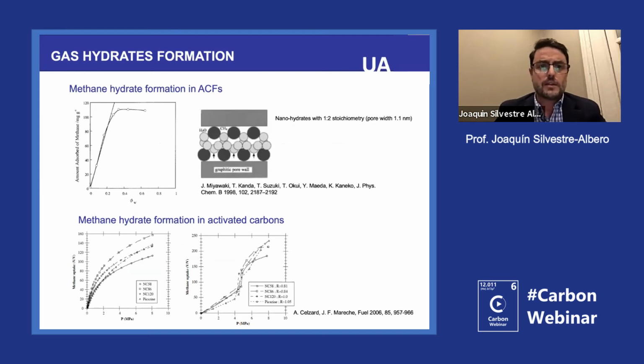There were already papers in the literature dealing with this problem. One of the pioneers is Professor Kaneko, in 1998. At this time, they were working with activated carbon fibers. And they were observing, as you can see here, that the amount of methane adsorbed can be improved when you incorporate water in the system. And you see that you have a linear performance. So the more you increase the amount of water, the more you can improve the amount of methane.